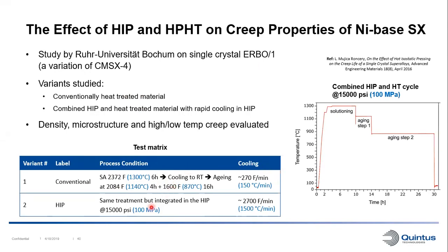We did the same type of treatment in the HIP system, with the difference that here we have the pressure at 15,000 psi. And also the cooling in the HIP system was around 2,700 Fahrenheit per minute, so much faster cooling than in the vacuum furnace. And we can see the log data from the combined HIP and heat treatment cycle here in the diagram to the right. So we have our solutionizing, cool down, first aging, and then second aging.